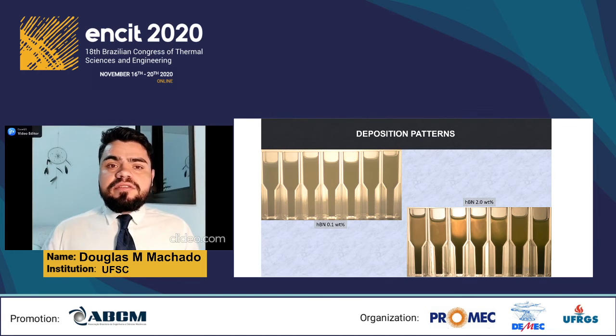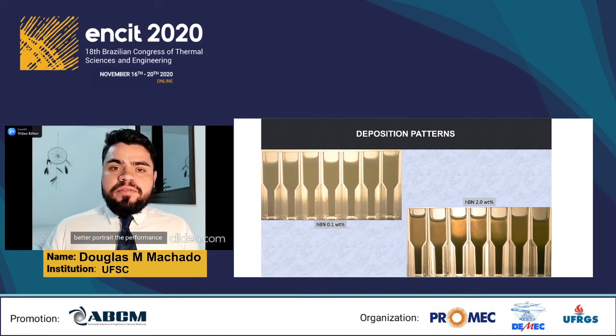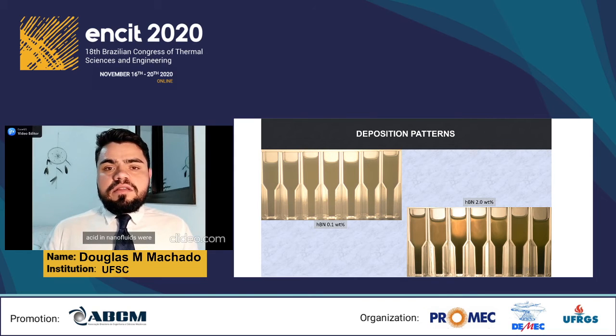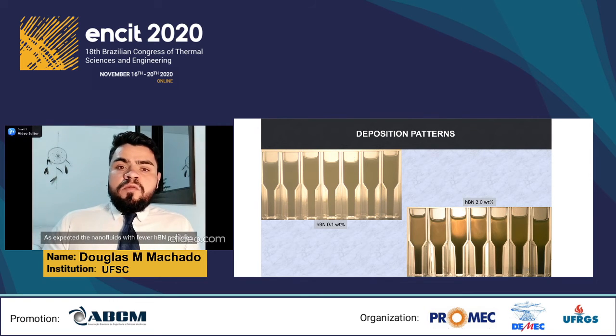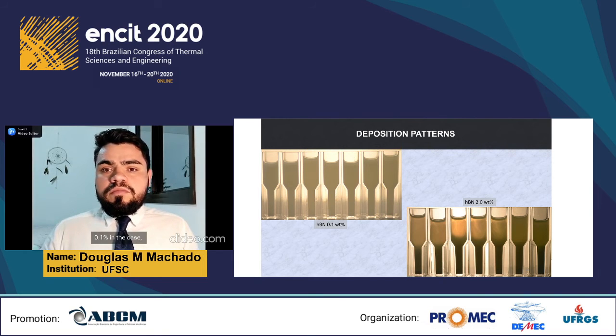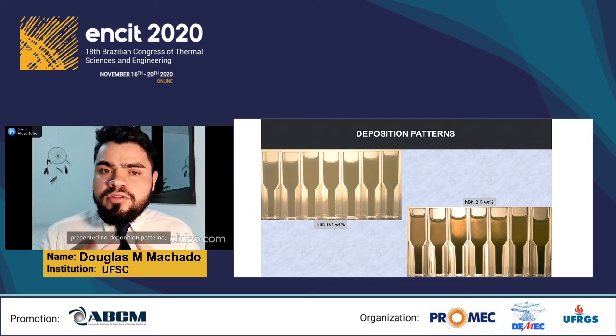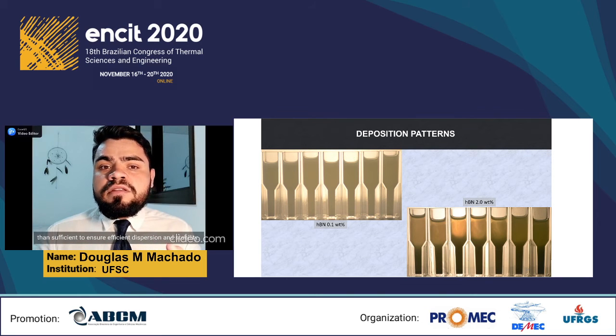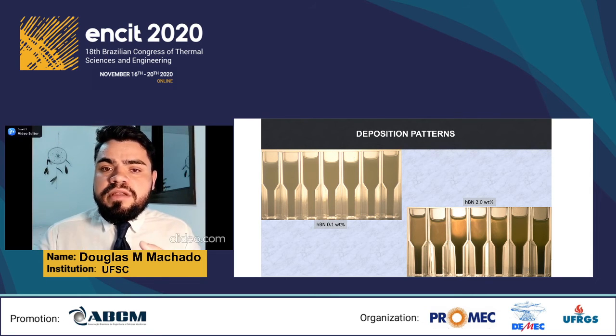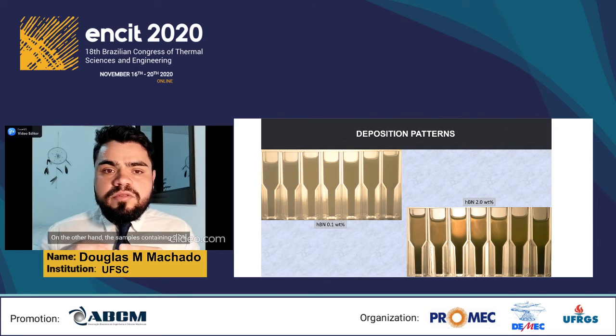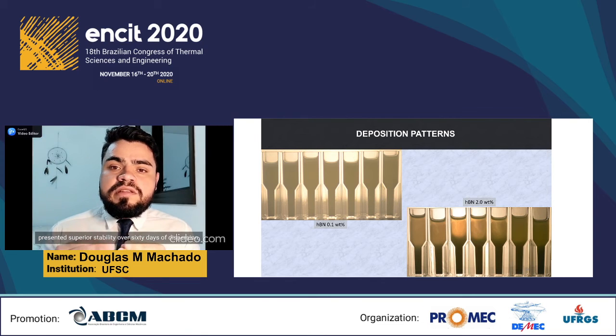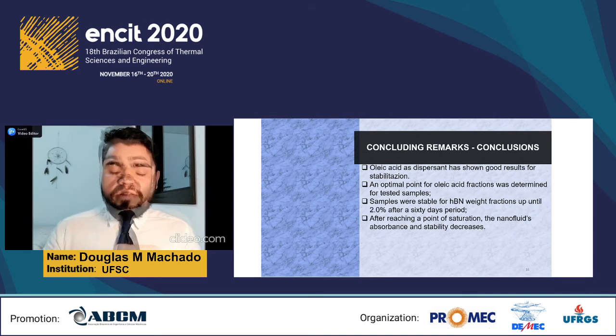60 days after the dispersion of nanoparticles in the base fluid, the samples which would better portray the performance of the addition of oleic acid in the nanofluids were put side by side. As expected, the nanofluids with fewer hBN particles, 0.1% in this case, presented no deposition patterns, so the considered oleic acid quantities were more than sufficient to ensure efficient dispersion and stability. On the other hand, the samples containing 2% presented superior stability over 60 days of dispersion, a remarkable result for this hBN weight fraction.